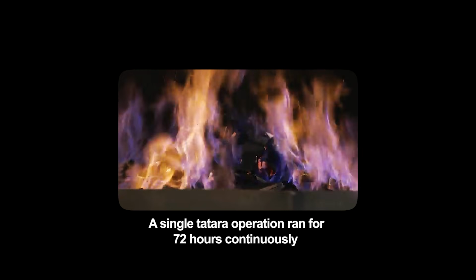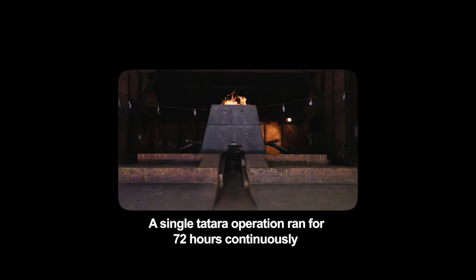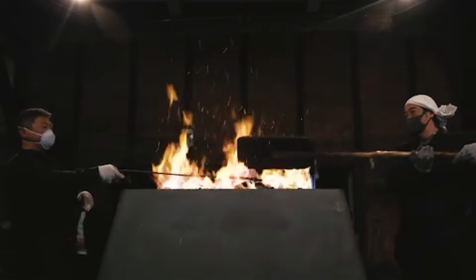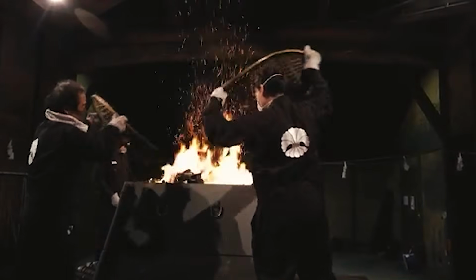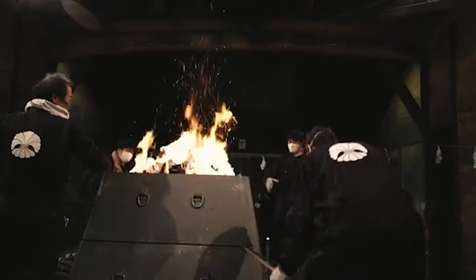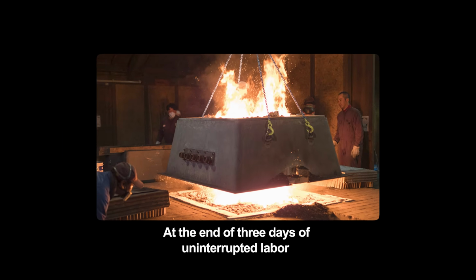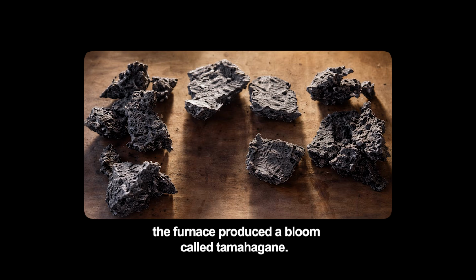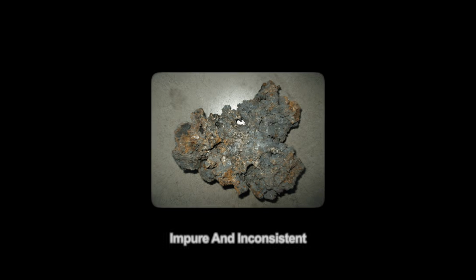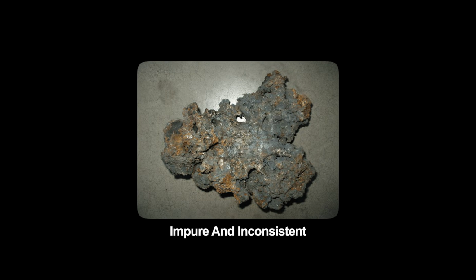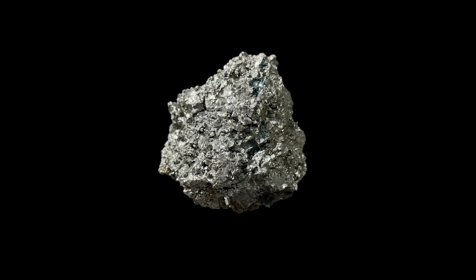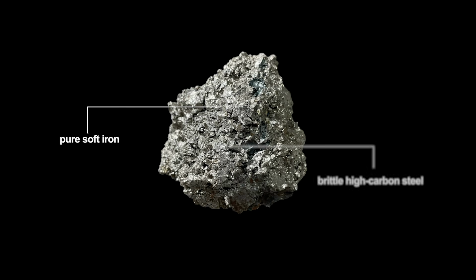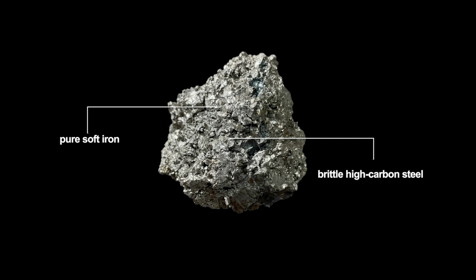It was not a quick solution. A single tatara operation ran for 72 hours continuously. Charcoal had to be fed at precise intervals. Temperature had to be maintained by teams working in shifts around the clock. At the end of 3 days of uninterrupted labor, the furnace produced a bloom called tamahagane, raw, inconsistent, full of impurities and slag. A single tamahagane bloom could contain steel ranging from almost pure soft iron in some sections to near-brittle high-carbon steel in others.